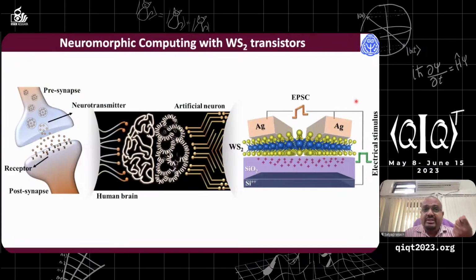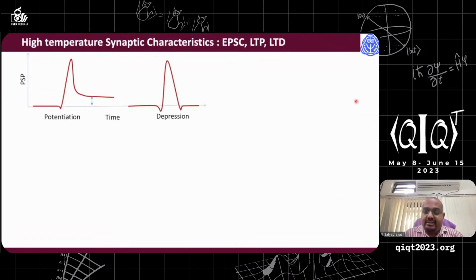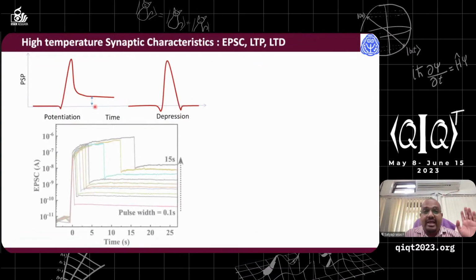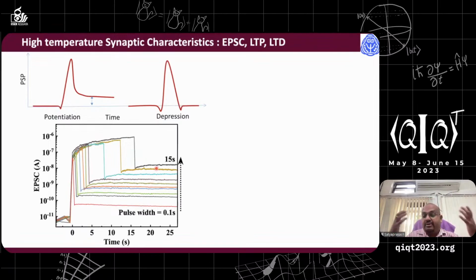Now I will try to show some of the more neuromorphic application of this WS2 transistor. Just to recall, when you have an external stimulus going from one neuron to another, it changes the potential, and this potential is the key for the memory. And here we have shown, just by applying a different pulse width, say from 0.1 to 15 seconds, we can systematically change the conductance state of this transistor. And this is the applied pulse of the gate voltage, just to remember. So by changing the pulse width, one can change the conductance state, which is very similar to what is achieved in the case of a neuron, where the conductance changes, and thereby a memory state is achieved.